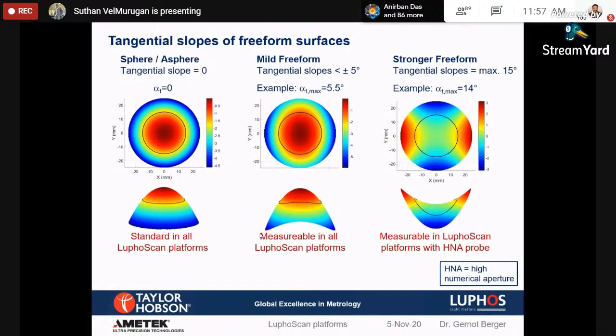This is one example of free-form measurement. The tangent slope is less than plus or minus 5 degrees. We call it a mild free-form or lesser free-form effect. So the standard LuphoScan machine and standard probe can measure it. If it is more than 5 degrees, up to 15 degrees, we may need a special HNA probe. HNA means high numerical aperture probe, which will go very close to the part so that the slope will be minimized. It can collect the reflection from the sample or from the optics, and then analyze it. So this is a special or custom-made solution available for free-form measurement.